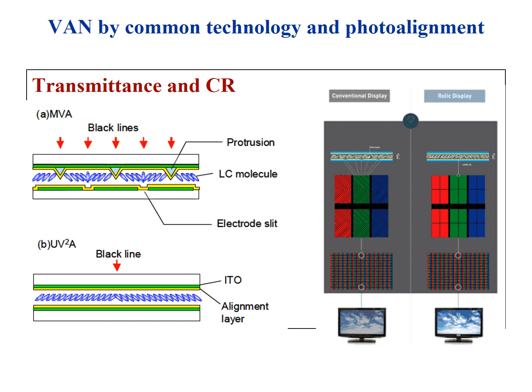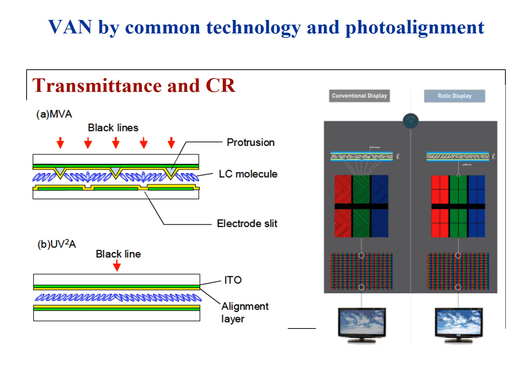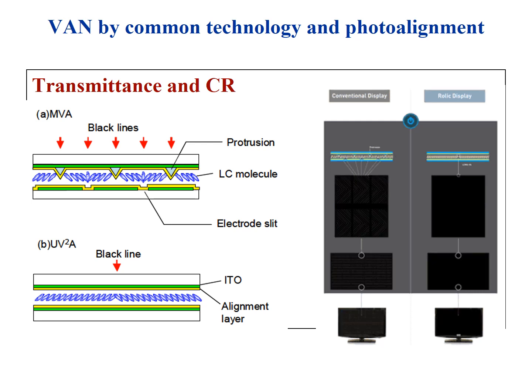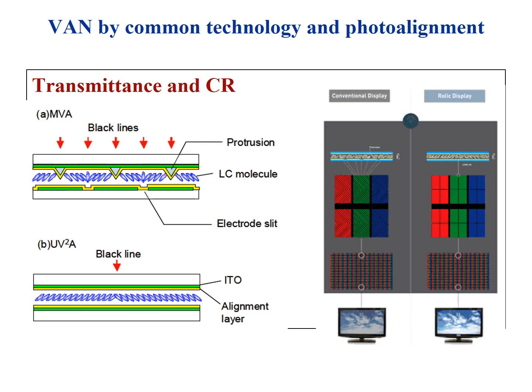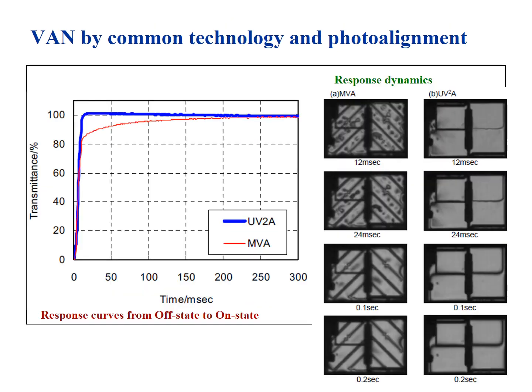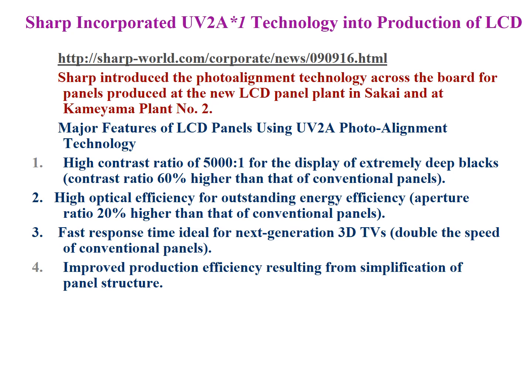And you can see, because we avoid the defects and we avoid patterning of the electrodes, from the picture that photoalignment, which is on the right side, is much better than the usual technology for vertical aligned liquid crystals, which are used for TV applications. Also, you can have excellent quality of transmittance versus time using photoalignment technology instead of the usual multi-domain alignment technology. So you can make different good things: high contrast ratio, high optical efficiency, fast response time.